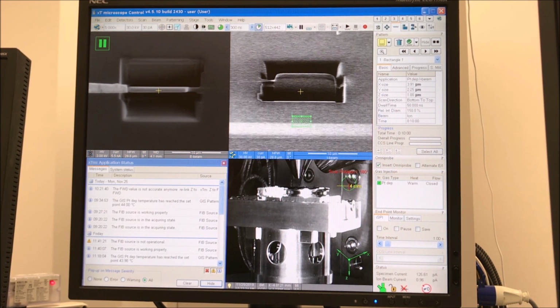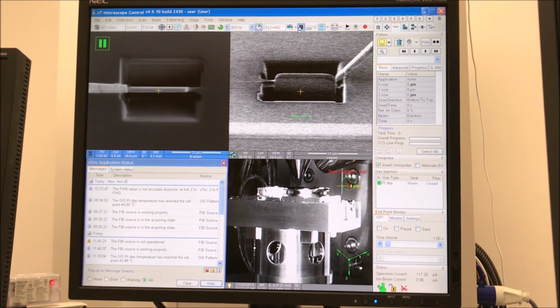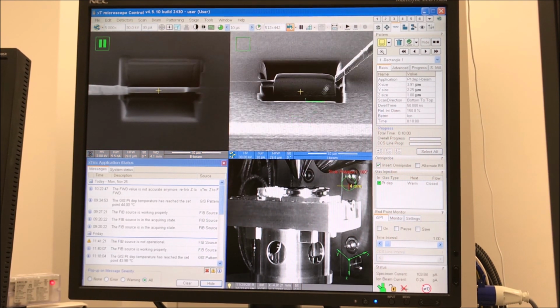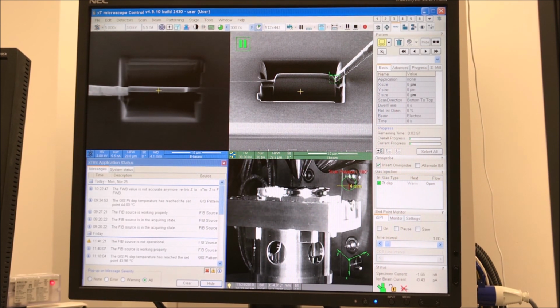So I also have a pattern here in the I-beam quad that's a rectangle defined for I-beam platinum deposition. So I'm positioning that omniprobe right there at the free edge of the lamella. I resize the box, and then I start depositing platinum. And so you can see this actually happen in the E-beam image, the buildup at the point of contact between the omniprobe and the lamella. And so you can run this until you get enough of a buildup and then stop.